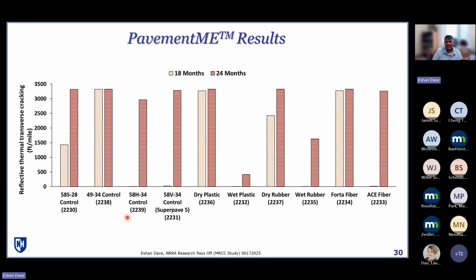In general, what we are seeing is that the control is actually showing not as poor properties as some of the modified mixtures, but that's also an artifact of how pavement ME works. It does not see or use any of your cracking results or indices. It's purely driven by your complex modulus. So it's a good demonstration that when it comes to things like cracking, especially reflective cracking, tools like pavement ME may not be as reliable, especially when you are doing some of these more innovative asphalt mixtures that are not like your traditional asphalt mixtures.